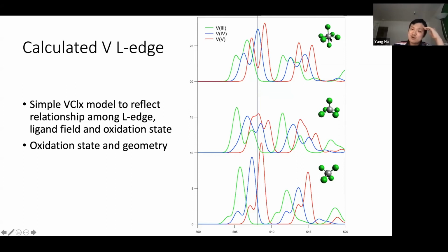And as we see, when we go from a perfect octahedral to a 5-coordinate or to a tetrahedral, even without a redox, the L-edge will tend to shift to a lower energy. So this means we have to consider both the redox reaction and the geometry. So here is a great example to show that the soft X-ray technique can also tell you something about the geometry, even though it's like an indirect probe.